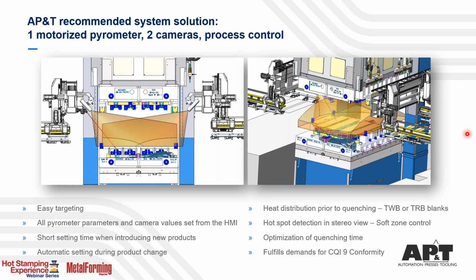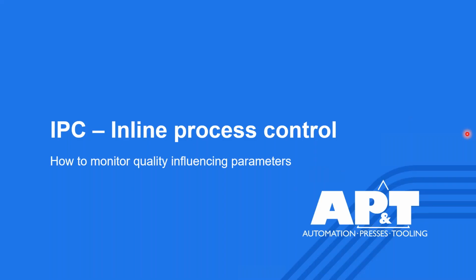The hotspot detection in stereo view after the quenching, after opening the die again, and the optimization of the quench time, depending on how much temperature you have left in the part when opening the die. And this system actually fulfills all the demands for the CQI9 conformity. Also interesting to know.